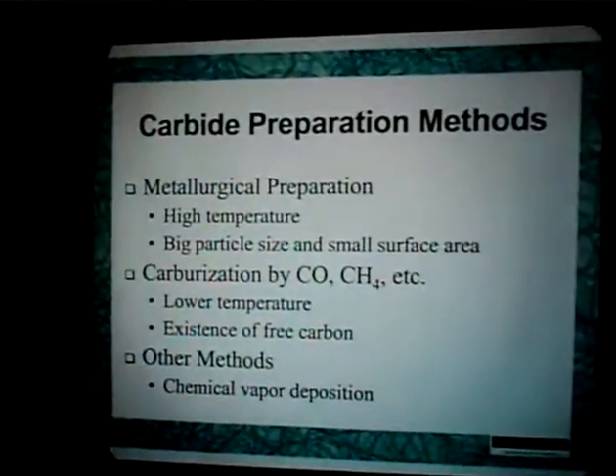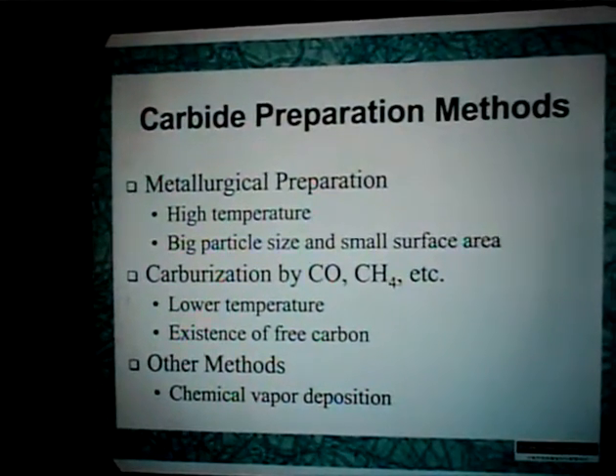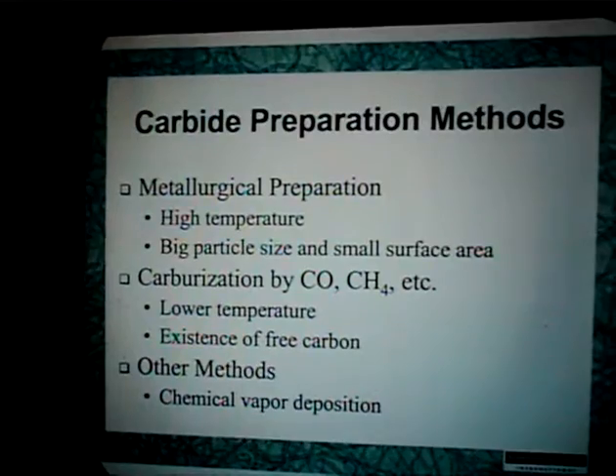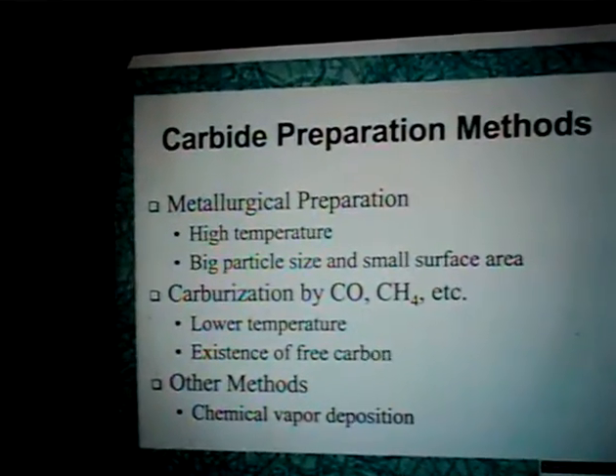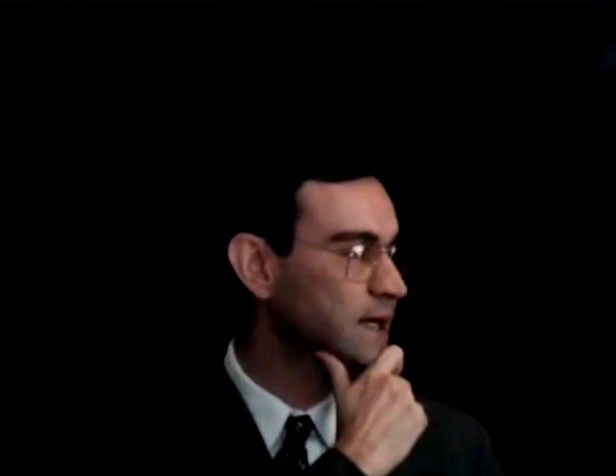So, the carbide preparation methods. This is a material that's used in many other applications in industry, for tools, etc. There is a metallurgical preparation, which involves high temperature, and there they are zeroing in on mechanical properties. In our case, we are interested in high surface area, also mechanical properties. Here the carburization is often done with a carbon source, CO or methane, at a lower temperature. Sometimes we end up with free carbon, but the methods of addressing that free carbon involve taking the heat away. And there are, of course, many other methods like chemical vapor deposition.